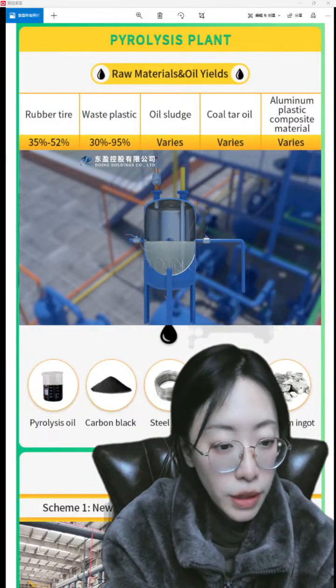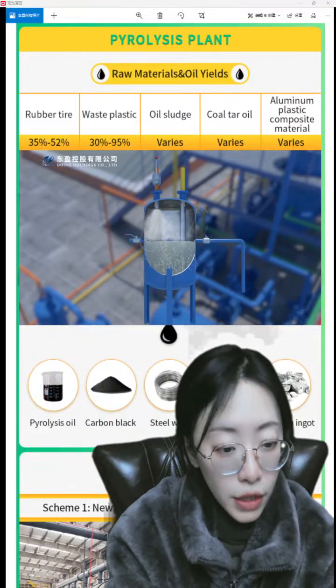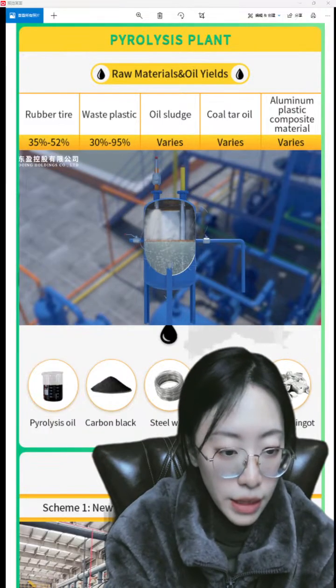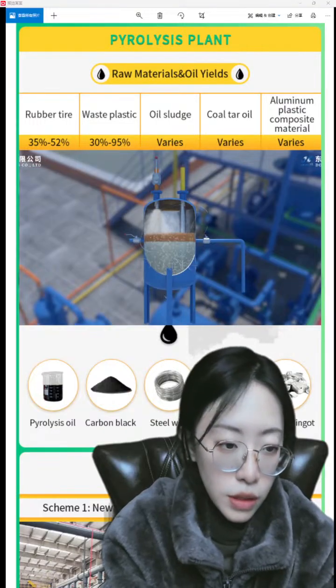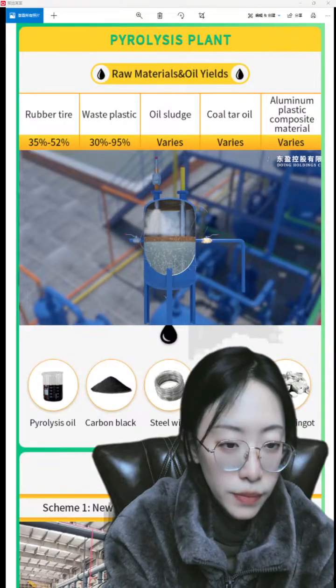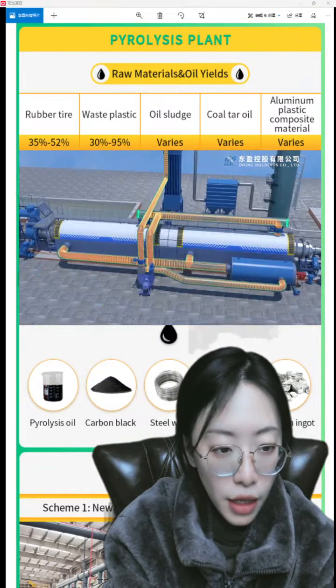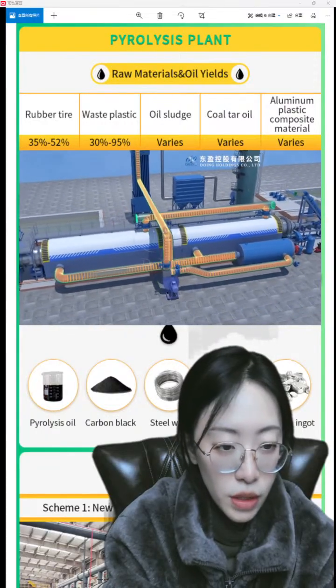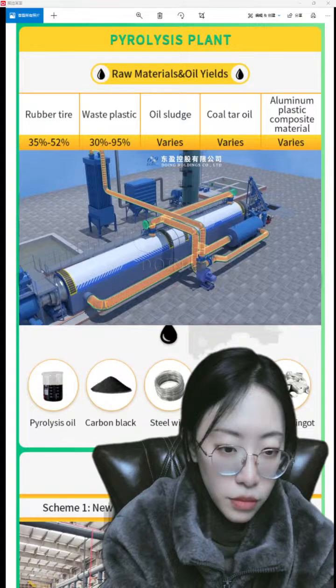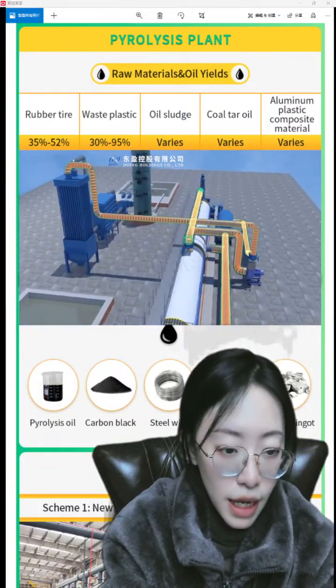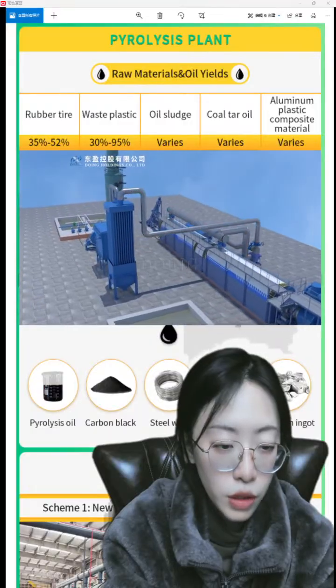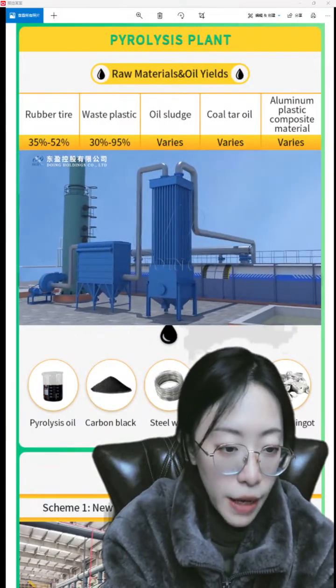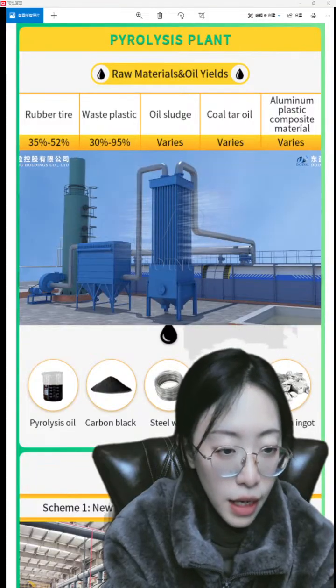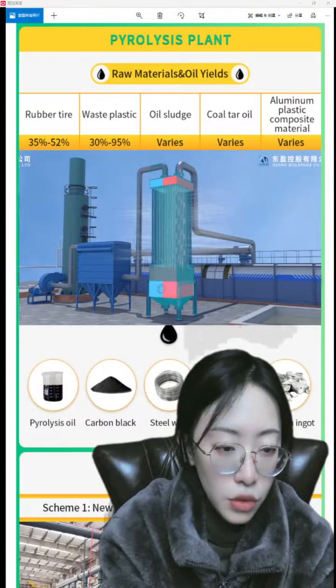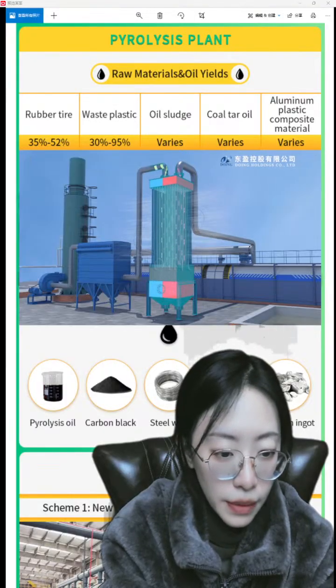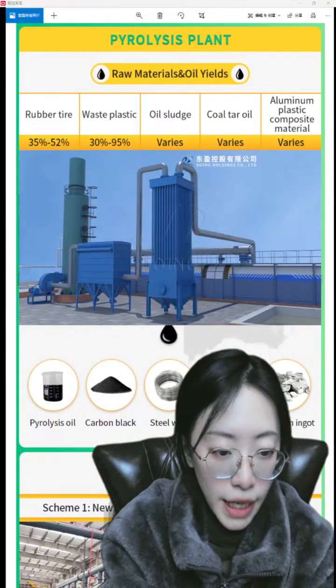So the fully continuous pyrolysis plant has the highest working efficiency and the biggest capacity. And it's more automatic, so it's suitable for large businesses or those with high daily raw material processing. Nearly 20,000 tons per year is more suitable for this type. And the daily capacity, a small one is nearly 15 ton, 20 ton. The most common ones are 20 ton, 30 ton, 40 ton, 50 ton. Most of our customers will choose the 50 ton per day.